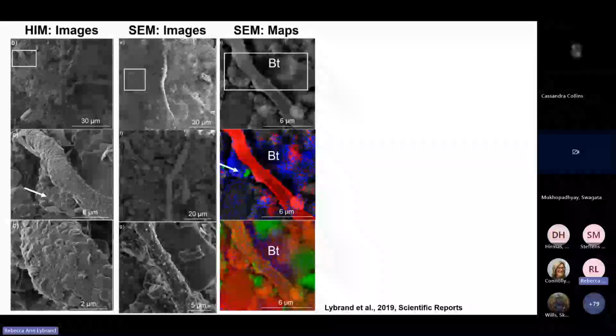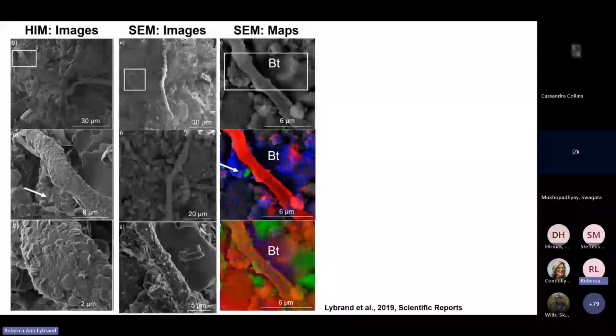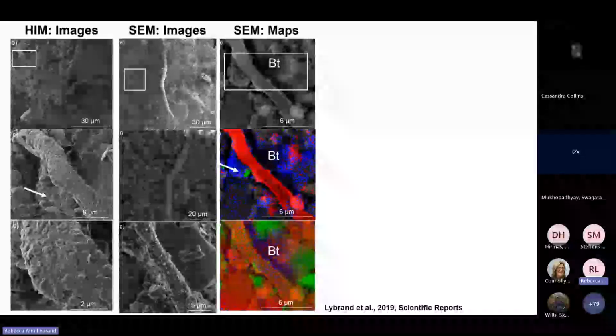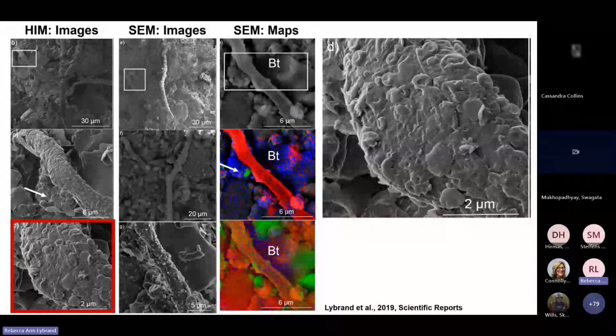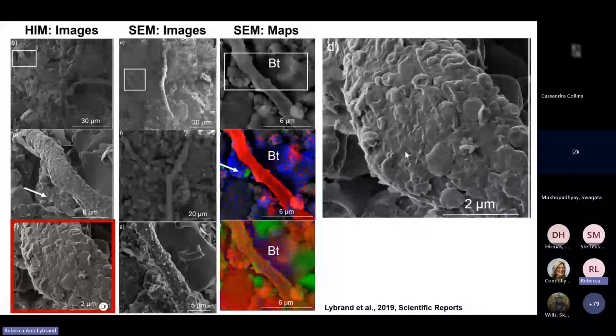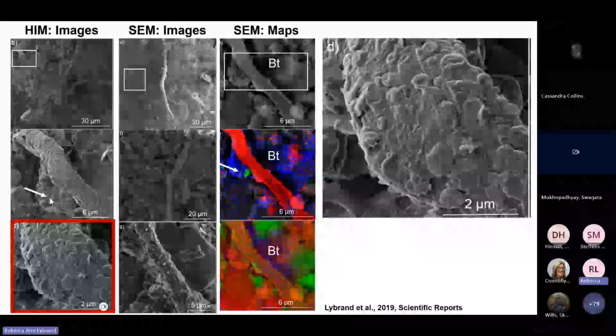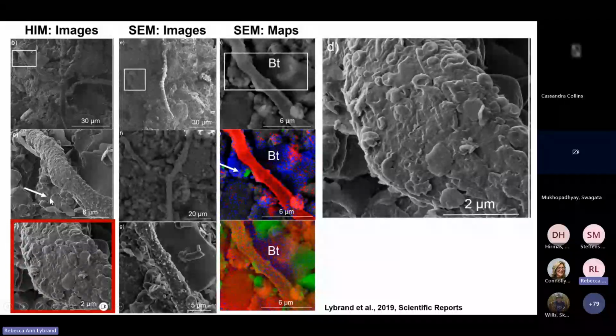We were able to use helium ion microscopy to capture these beautiful images, especially of biological samples. And then we were able to go back to that same interface, which caught our attention here really quick. If you draw your attention to where my cursor is, this white arrow, we saw this fungal structure, but we were asking, what is this material that's adhered to the fungal structure? And also, what grains are associated with this contact here? The helium ion microscope gives you this phenomenal imagery, but not the chemical information.